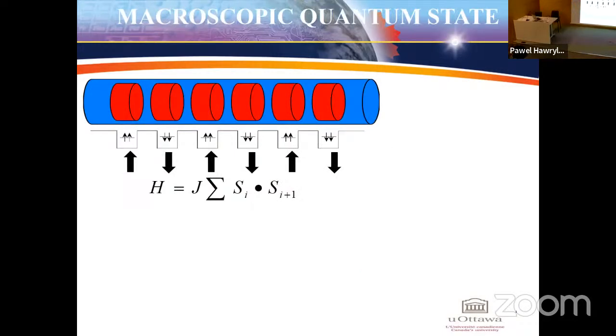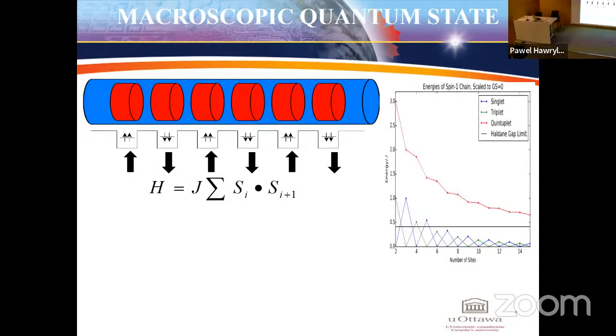We are on the way to study this spin 1 chain. So now we just studied the spin 1 chain, and what do we see? As a function of the number of these quantum dots of spin 1s, we have an oscillation between singlet and triplet, which goes down to 0.